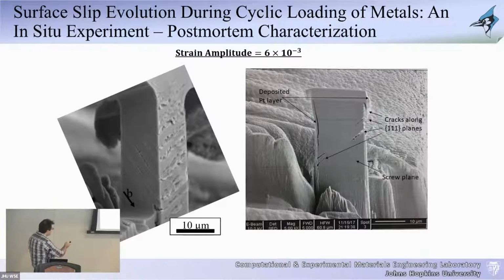cracks that are propagating. So what we did is we cross-sectioned this sample. If you look through the cross-section, what you see is these cracks that are forming along each one of those bands that are forming. And these are these small, short cracks that initiate in the material. Not each one of them is going to propagate and lead to failure. Eventually, one of them is going to dominate and lead to failure, as I'll show you in the next slide.